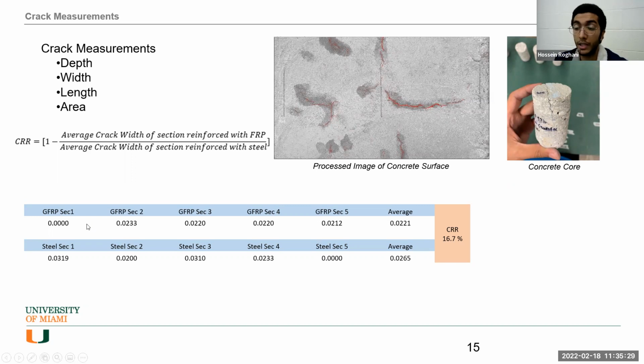In one of them, we had the GFRP, which is the glass fiber reinforced polymer. It's one type of our reinforcement. And on the other side, we had the conventional steel. Both of them were number three reinforcement, which has a diameter of 3/8 inches, and the spacing between the rebars was the same, 12 inches. At the end, after the image processing and using the CRR formula, we came up with the result that the